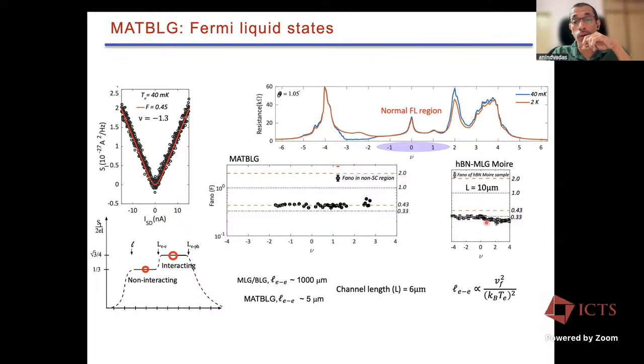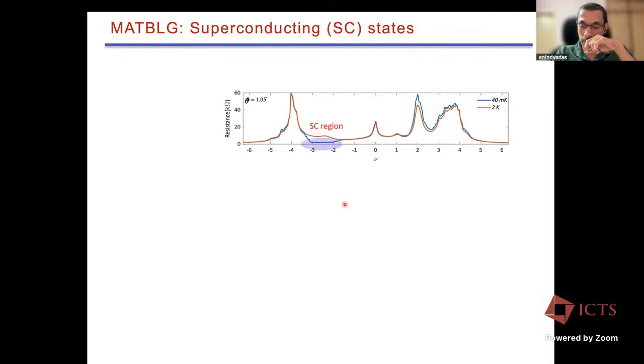We found the Fano is 0.33, which is expected, because in this system the transport is diffusive transport. The electron length scales are much larger at this temperature. On the other hand, in this flat band, since the electron interactions are stronger, we see the universal Fano of 0.43 in these systems. So after this, we look at the superconductivity regime.